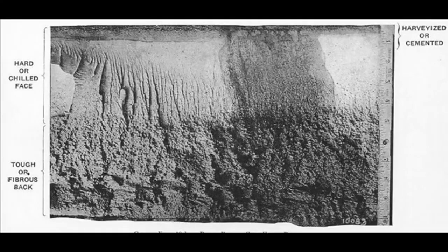What this eventually did is to cause carbon from the charcoal to seep into the steel, kind of a reverse process to the puddle furnaces that were designed to remove fuel-based impurities. Now you were using fuel to try and bring those impurities back in, or specifically the carbon part at least. As the steel never actually went molten, this higher carbon content was most present in the upper face of the plate, and decreased relatively rapidly the further in that you went.